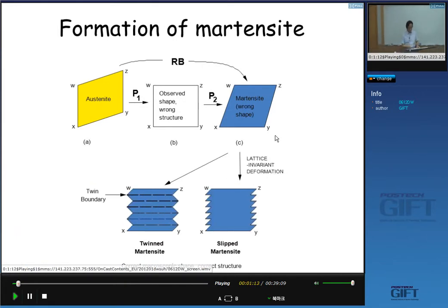To remind the core concept of the martensite transformation, let's start with this slide. I told you that the lattice strain which converts FCC into BCC is an invariant line strain, which is the combination of bain deformation and rigid body rotation. But what we observe in experiment, the shape deformation associated with FCC to BCC, is an invariant plane strain, because we can observe the habit plane, which seems to be invariant before and after the transformation. So to fill the gap between what we observe and what theory tells you,